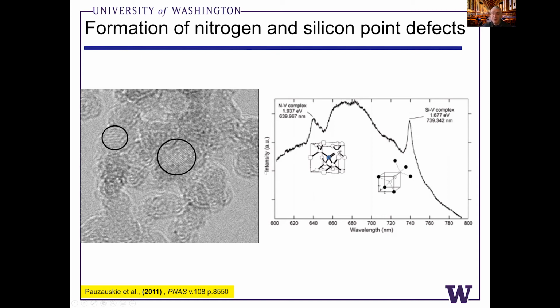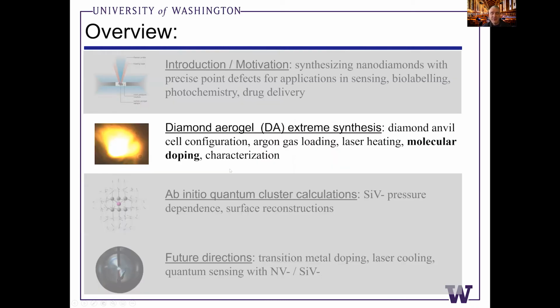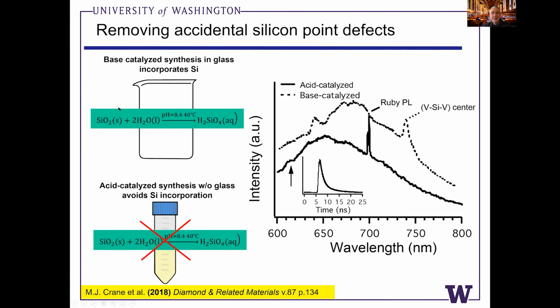And more recently, my group's been focusing on how can we control these defects? Where are they coming from? And how can we get rid of them and then add them back with molecular control? So the first defect that we focused on is the silicon split vacancy. We really weren't sure why we were getting silicon when we hadn't added it to our reaction. But in our initial sol-gel reaction process, we had added all of our reagents within a silica beaker in basic conditions. And if you have a basic aqueous medium in glass, effectively you etch away the glass at least at ppm levels. You can dope accidentally, inadvertently, by etching your silica glassware.